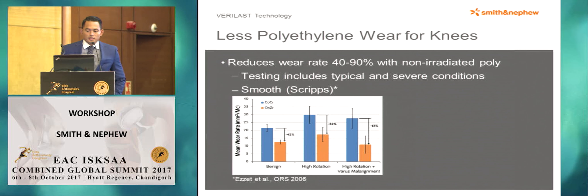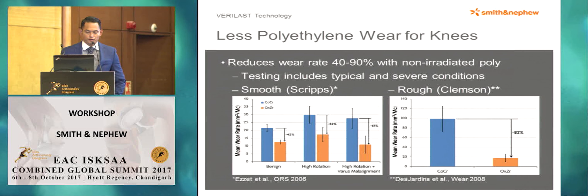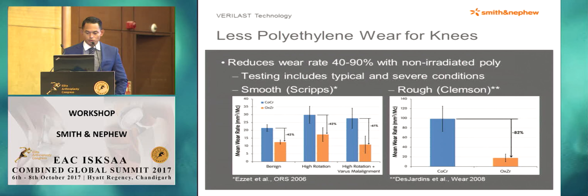This technology, as shown by one of my colleagues at Scripps in San Diego — my neck of the woods — reduces the wear rate from 40 up to 90 percent with non-irradiated polyethylene. This testing includes typical and severe conditions. Under smooth conditions, the oxidized zirconium had a much less wear rate than traditional polyethylene and traditional cobalt chrome. Also shown in a rough situation, the wear was much less.